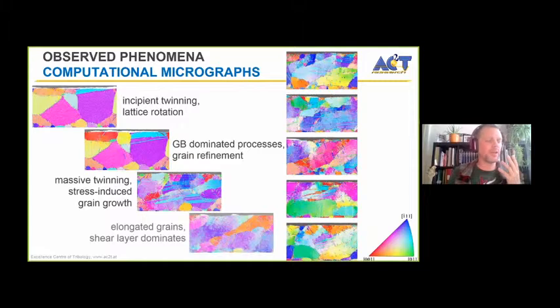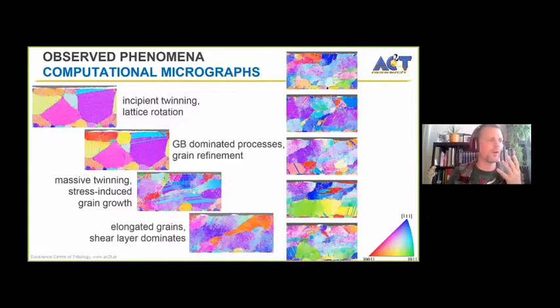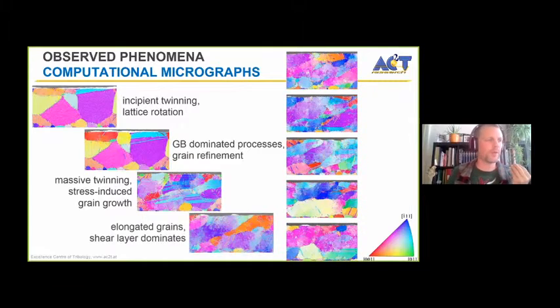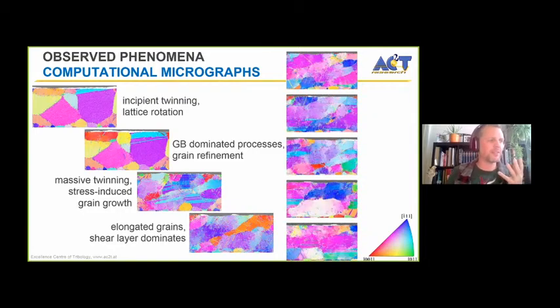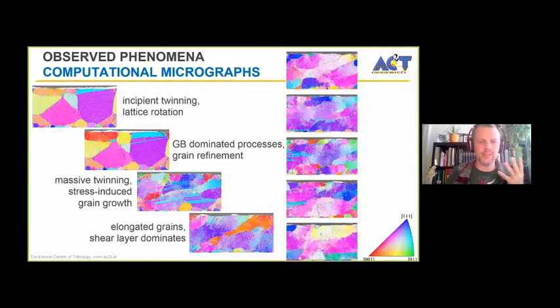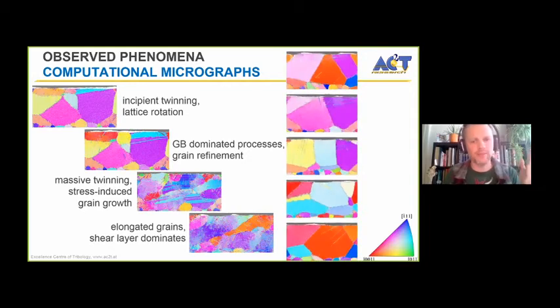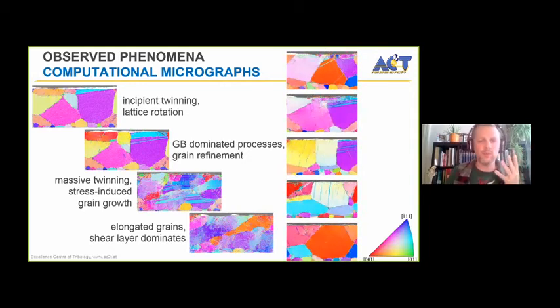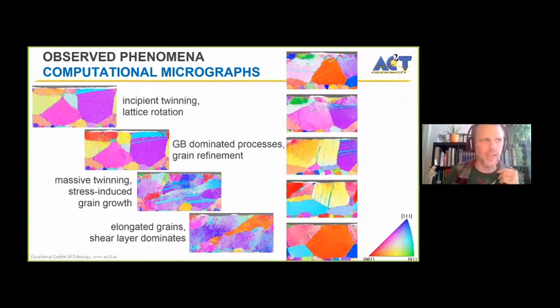And finally, we come to the limits of our system. At some point, the shear layer that starts forming elongates your grains and it dominates the behavior of your entire system. Basically, you have sort of a Couette-like flow. It's more like peanut butter at this stage. So basically, we've hit the end of what we can simulate with a thickness of 40 nanometers.